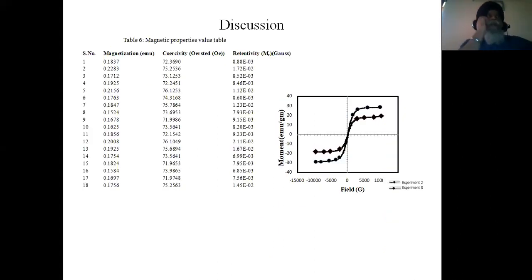Here, actually, I am interested in making smart tiles which can be used for self-assembly purposes. So what we did, we selected PLA, which is a biocompatible thermoplastic. Then we used recycled PVC, which is used in the paneling of offices, cabins, and all. Then Fe3O4 for some magnetic properties, and wood dust for thermal insulation properties. And we measured their magnetization property.